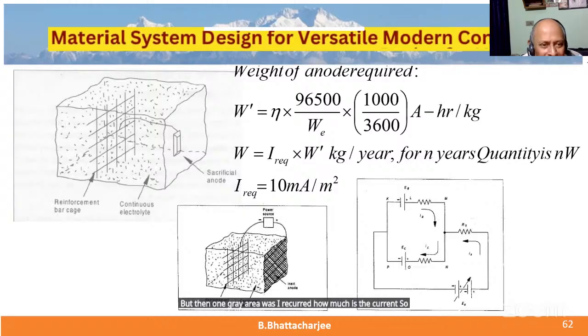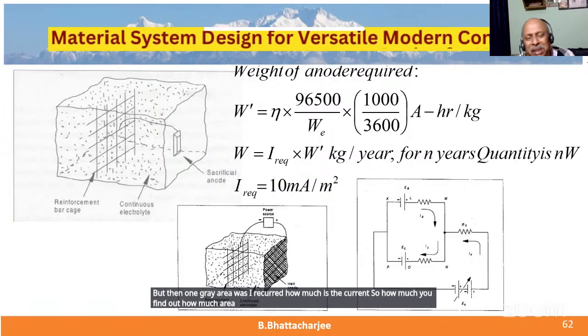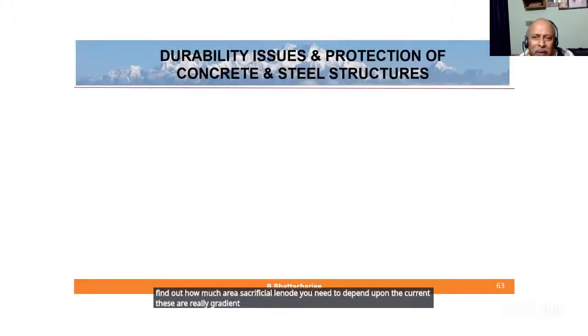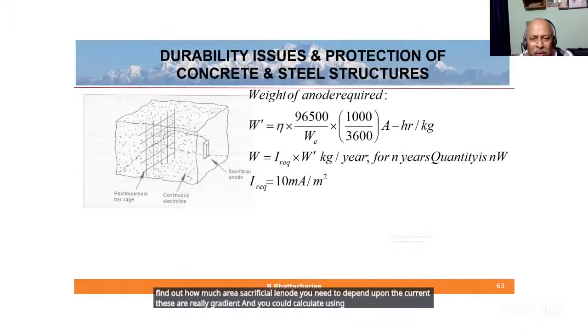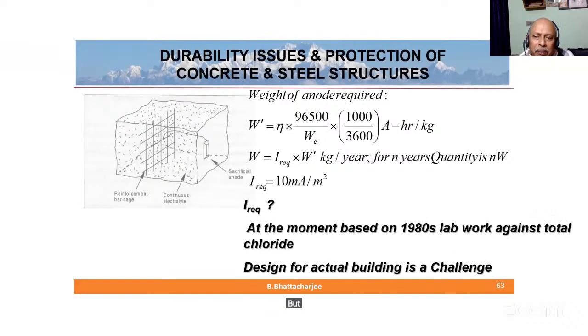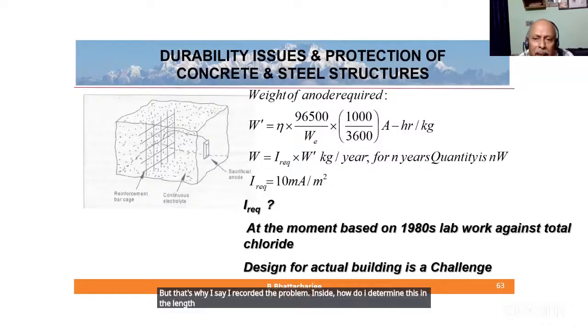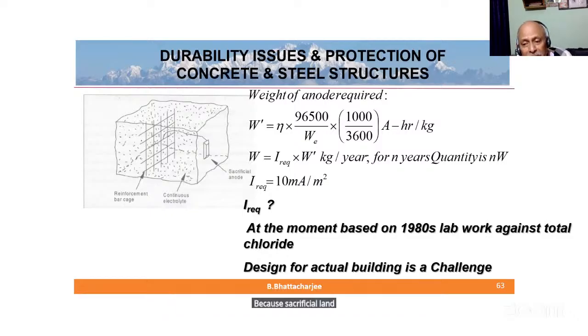So how much area of sacrificial anode you need depends on the current. This is a really gray area. And you could calculate using Faraday's law. I'm not going into that. I required is a problem. Inside buildings, how do I determine this? And when there is internal chloride all over the place, if I miss a place, it will be there. Sometimes the system does not work. Monitoring is minimal because the sacrificial anode will get consumed.